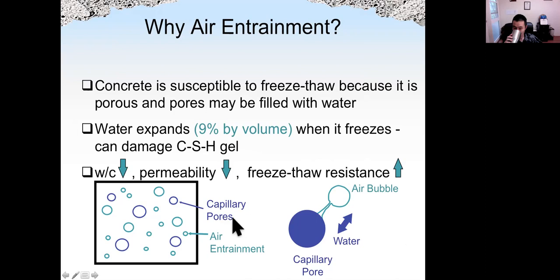So when we introduce these tiny air bubbles, which are shown here in these green circles, this air is empty inside, and we have water in capillary pores. The capillary pores are shown in these blue circles. So when water freezes, the 9% increase in volume will try to find some space, for example, these air bubbles. If that happens, the stress will be released, so concrete will not crack. So that's how air entraining agent works to reduce the freeze-thaw damage.